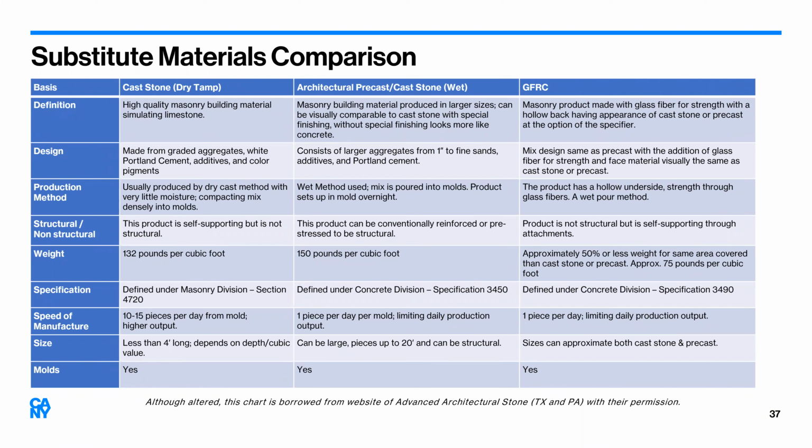Can you address the differences in thermal coefficient of expansion between terracotta and the substitute materials and how that would influence detailing? Yes, they do have different coefficients of expansion and contraction, and basically what you do is you create space. You put space between your terracotta and your replacement substitute material, and you isolate them, whether that be with waterproofing membranes, backer rods, joint pads, or silicone joints. There's just a variety of ways to give them the space they need to not compress and break your original terracotta.